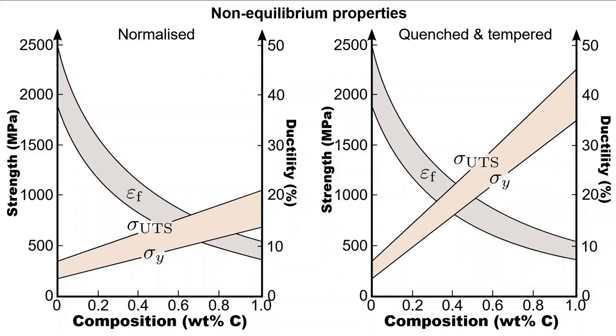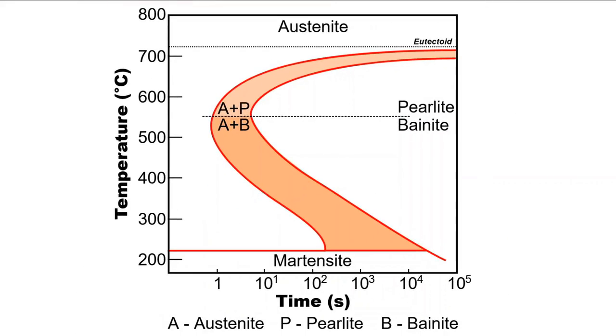Let's look first at what quenching does. We know that non-equilibrium phases cannot be represented by a phase diagram. The way that we can predict what phases will appear in relation to time at a given temperature can be represented with a diagram that looks like this. I showed a less detailed depiction of this continuous cooling transformation, or CCT, diagram in an earlier lecture. This diagram shows that as different temperatures are maintained for a particular period of time as the material cools, it reveals the different phases that will form. We won't go into how much of each phase is formed, as this is beyond the scope of the course, but this is also possible with a CCT diagram.